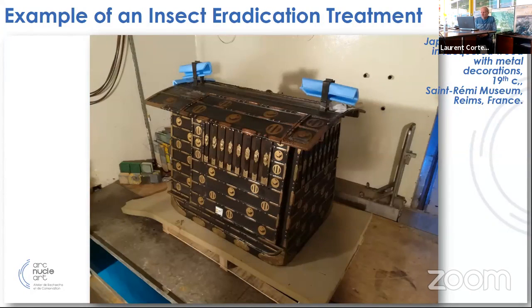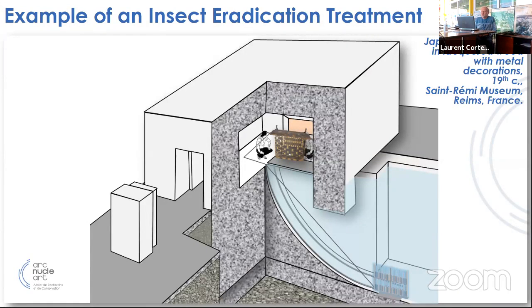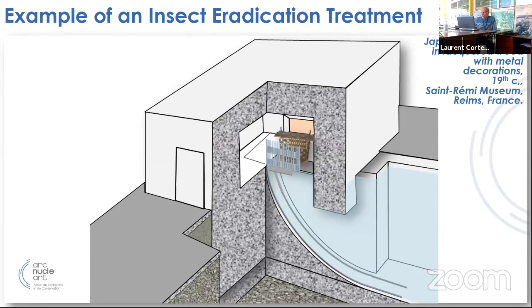So how do we proceed? I will give this example of the irradiation for insect eradication we did recently on a Japanese palanquin with lacquered wood. Firstly, we have to set up the artifact in a place in the bunker, in the irradiation chamber, where we know the intensity or dose rate of radiation. Then we evacuate the chamber, close the door, and pull up the source into the irradiation chamber to initiate the irradiation.